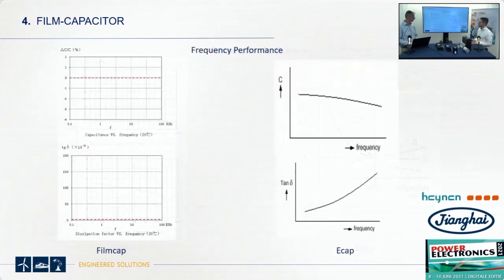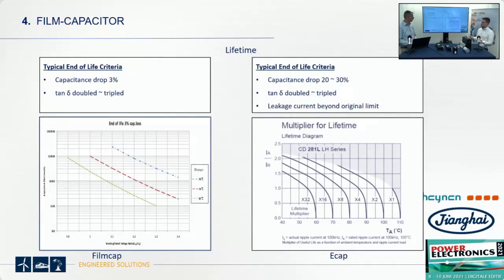Okay. The same for frequencies. For frequencies, especially at high frequencies, the film cap is also stable. Nothing has changed. The capacitance is stable. The dissipation factor is stable over different frequencies, and on the other side, the ECAP is changed. Its capacitance and its dissipation factor change at different frequencies. And therefore, we use film capacitors in the high-end application with high frequencies, high currents, and high requirements of the application.